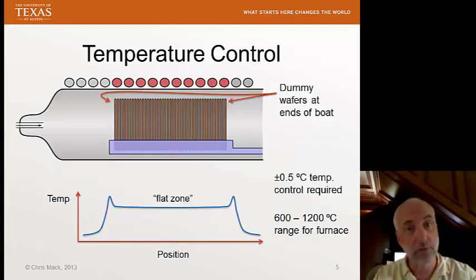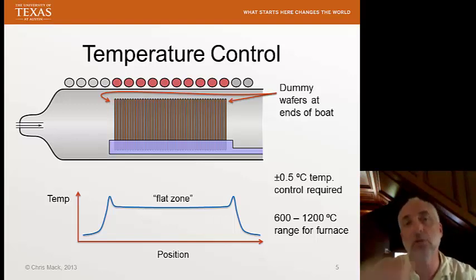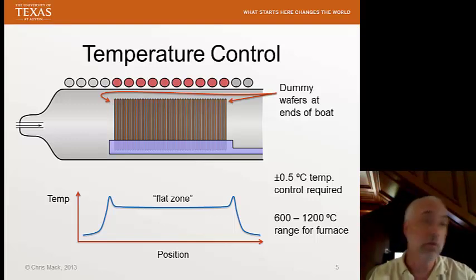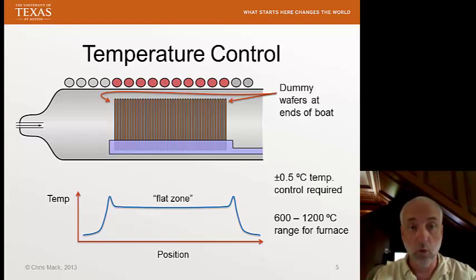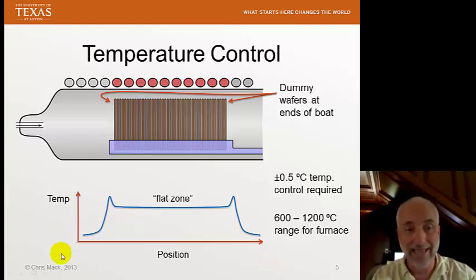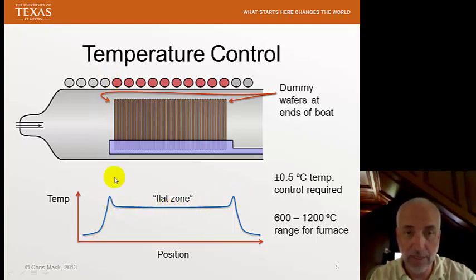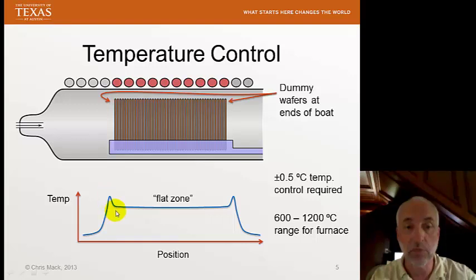One of the most important aspects of a furnace is temperature control. We have a number of temperature heating coils wrapped around the tube, each individually controlled so we can adjust the temperature. What we want is a uniform temperature across all of those wafers. If we look at temperature versus position, eventually where there are no heating coils the temperature drops. To get a maximum flat zone, we take the last temperature coil and heat it higher than needed so it ramps up a little bit and then falls down — that gives us the best flat zone.